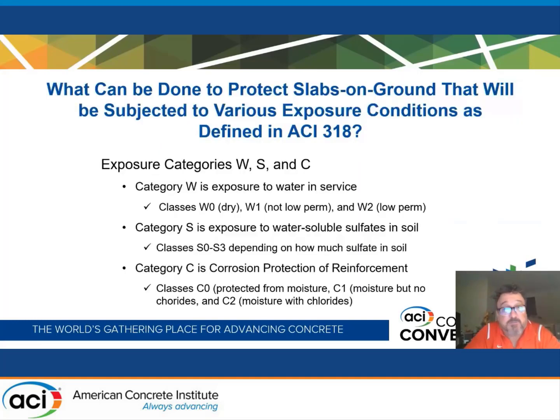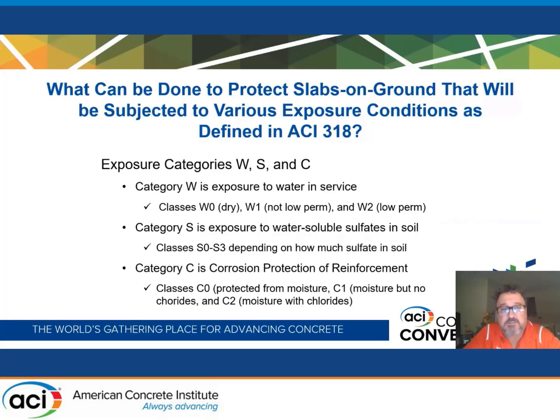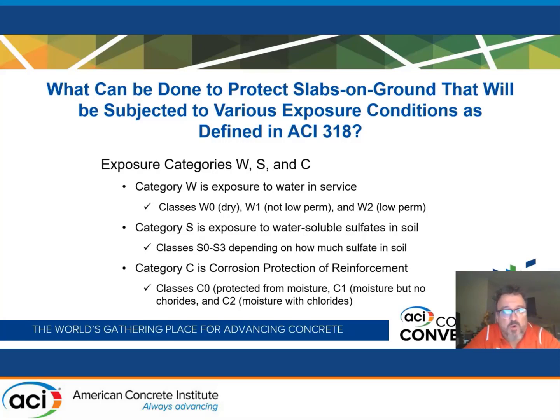The other exposure categories are W, S, and C. They all revolve around the water content — the resaturation or amount of water allowed into the concrete slab. Category W is exposure to water in service; Category S is exposure to water-soluble sulfates in the soil; Category C is corrosion protection of reinforcement. Within each category there are classes from zero to one, two, or even three. You start at zero — which is dry — and increase to class one, two, or three depending on the amount of water in contact with that slab.